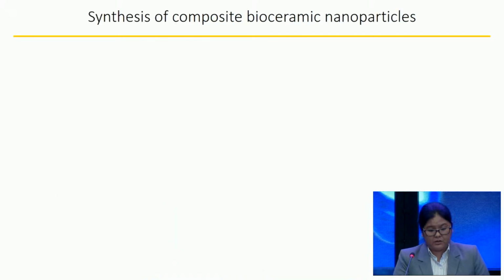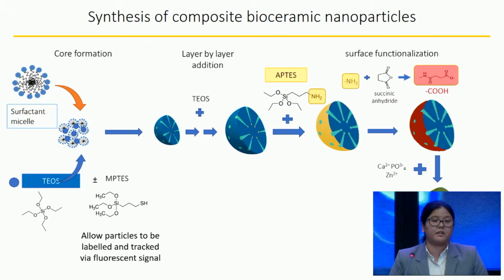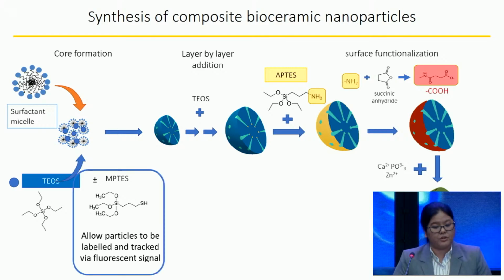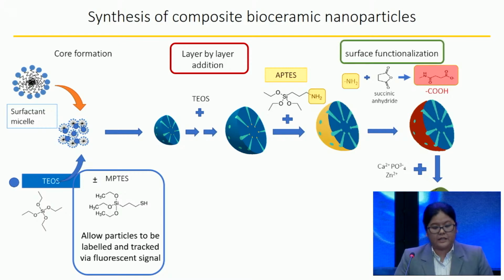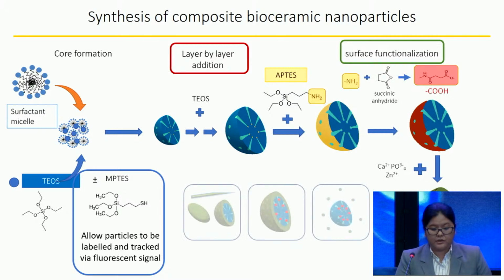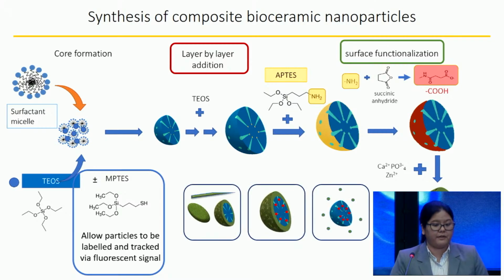While nanoparticles could be synthesized via various methods, we use a modified co-condensation method, which allows relative ease in modifying the core, which allows particle tracking, controlling its size via layer by layer addition, and functionalizing the surface to create a calcium phosphate coated mesoporous nanoparticle. This method is used in Chapters 3, 4, and 5.